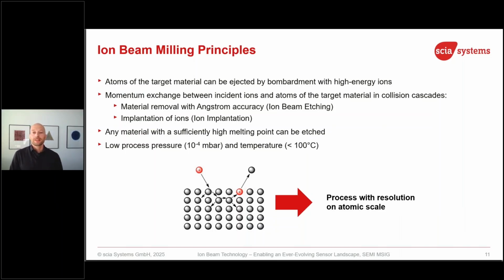So basically, ion beam etching is a physical sputter process. We have ions with an energy of a few hundred electron volts hitting a surface, initiating a collision cascade, and then with some luck, one of those atoms is leaving the surface, and this is called a sputter process. Depending on the kind of ions, on the binding energy, and so on, the yield or the sputter rate is different. The big advantage compared to chemical etching is that the process is working on any kind of material. If you can put this material into the vacuum, then we can do ion beam etching on it. It's working at rather low pressures, so we have long mean free paths, and processing temperatures are also relatively low.